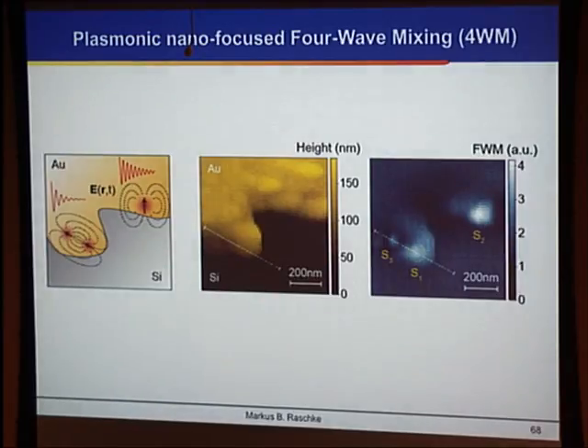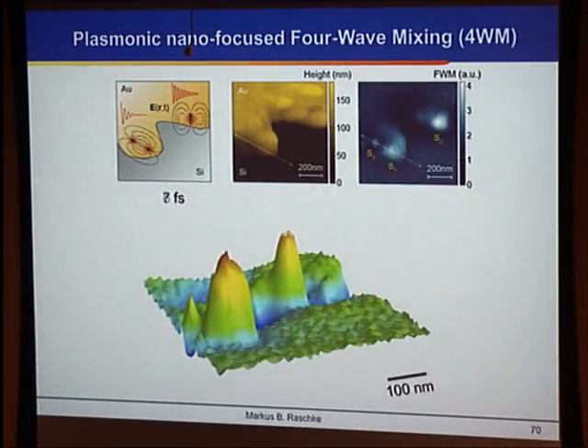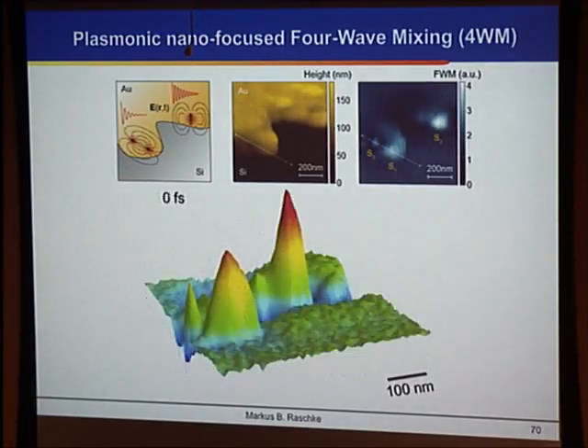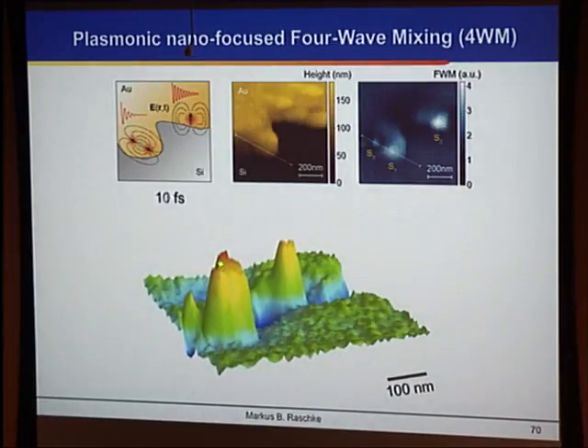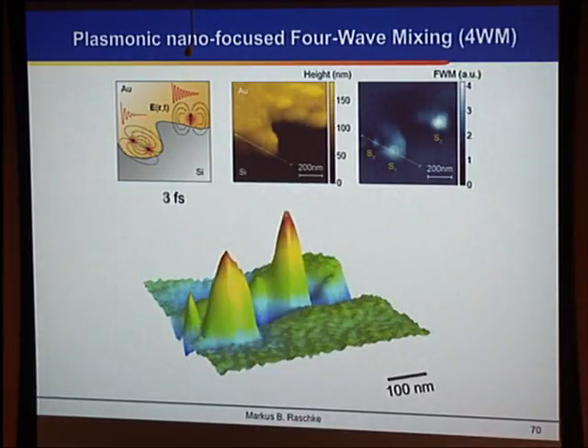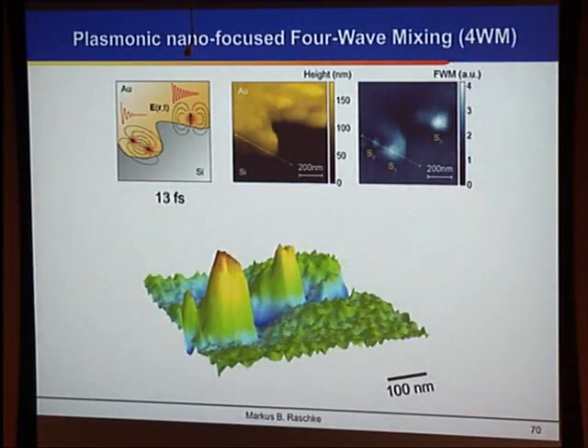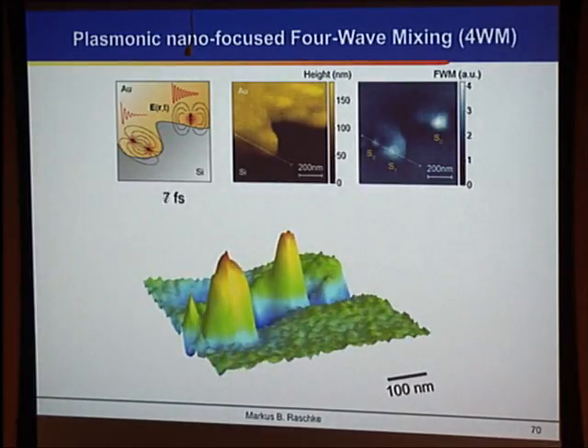And so what we'll do there, we have multiple pulse sequences, which then leads to the coherent generation of this four-wave mixing signal. And as we pulse delay one with respect to the other, we can essentially turn a movie. And so what we do here is we normalize the signal to the center emission of this, and then you'll see that really as we are stepping through, this is with single cycle precision.